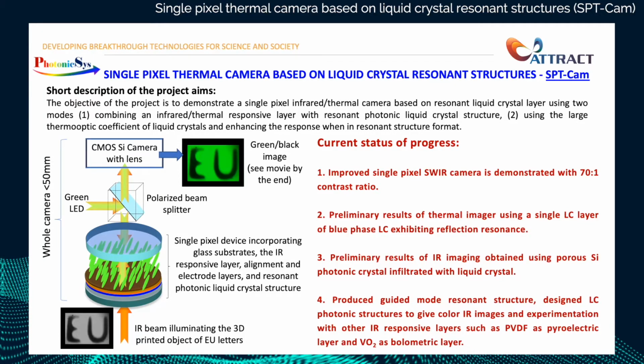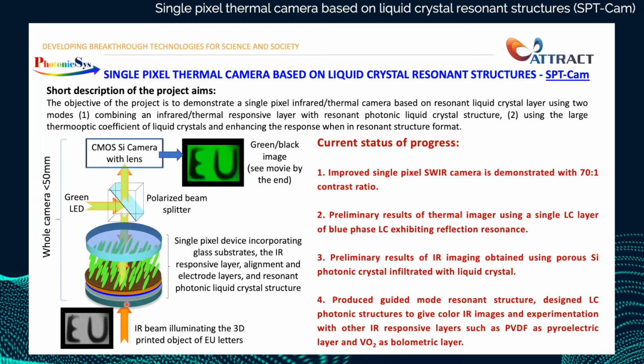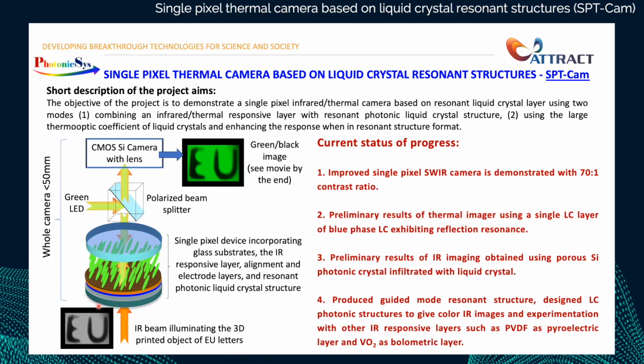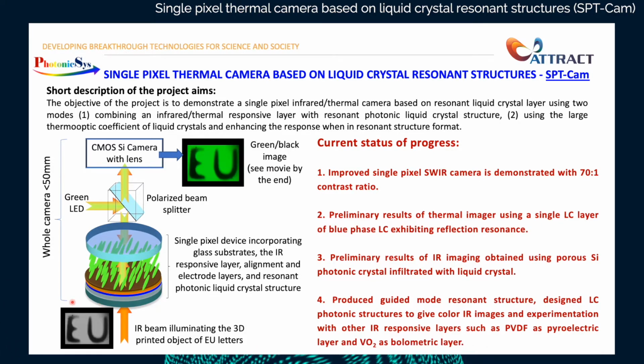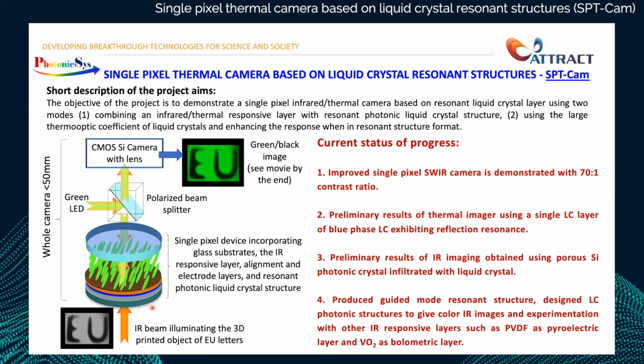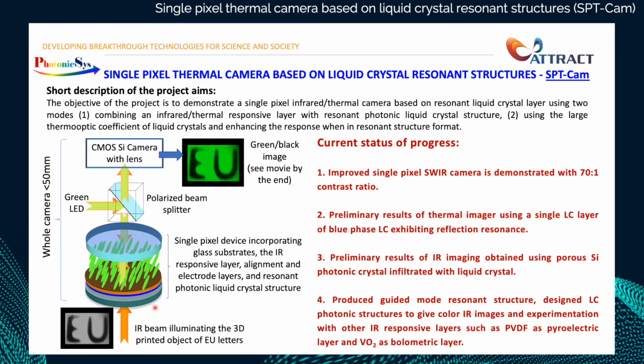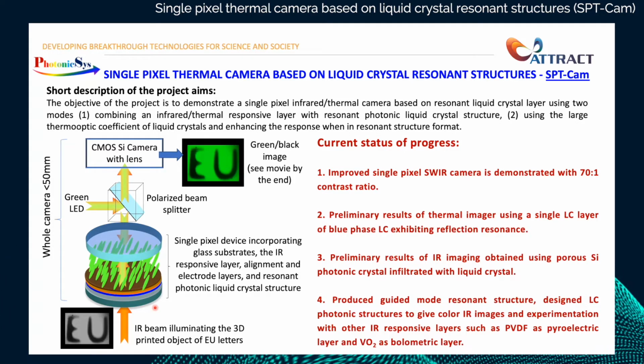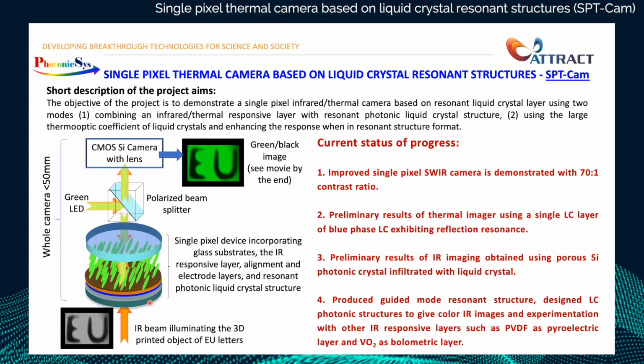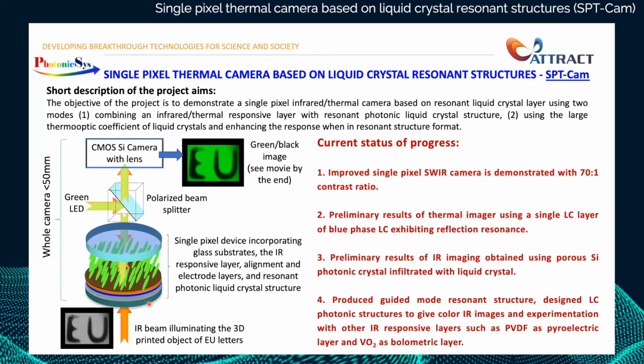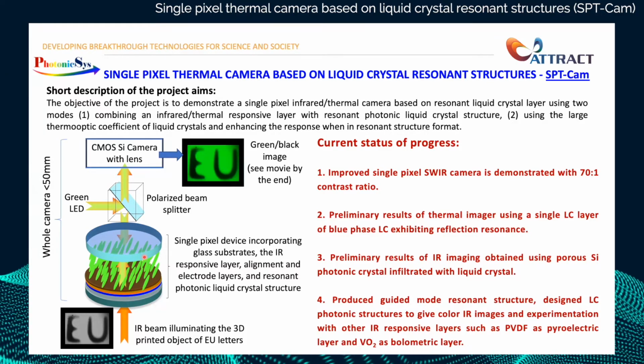So in this figure here, we can see the main device, which is composed of two glass substrates, and one of them is coated with the IR or thermal responsive layer. And of course, there are additional layers like transparent electrode, alignment layer, and thin film layers for the resonant structure, and of course the LC layer. This whole device can be less than 1